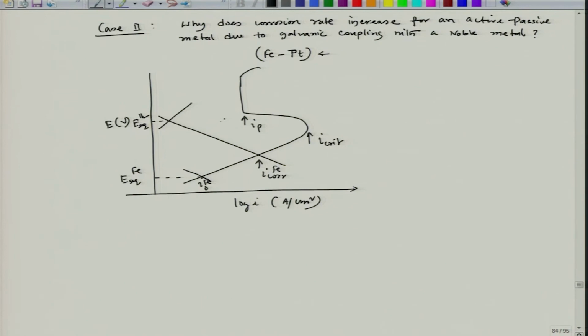So that increases, let us say the increment is here. This becomes the new exchange current density of hydrogen on platinum surface, and this becomes my hydrogen I0 on iron surface.